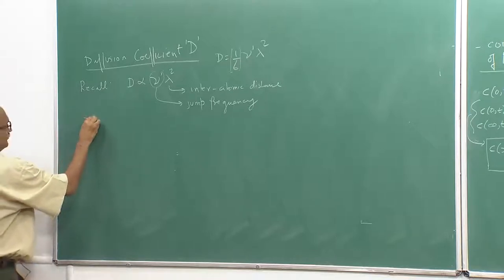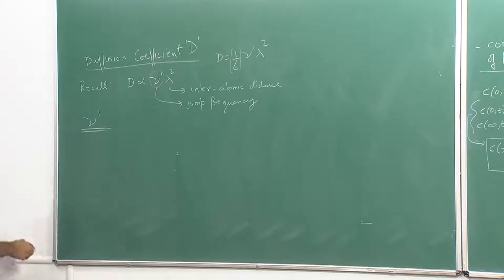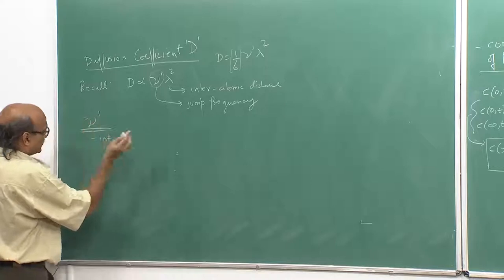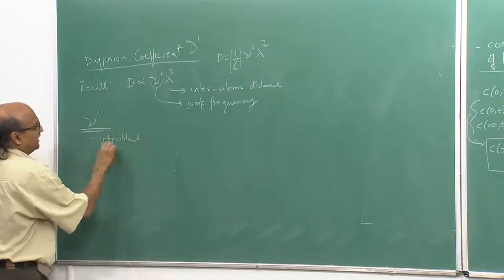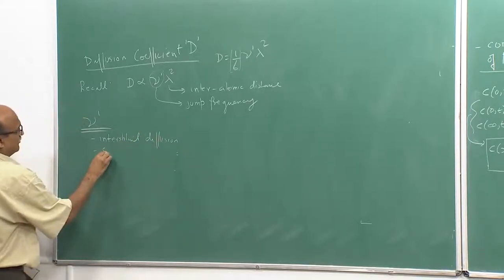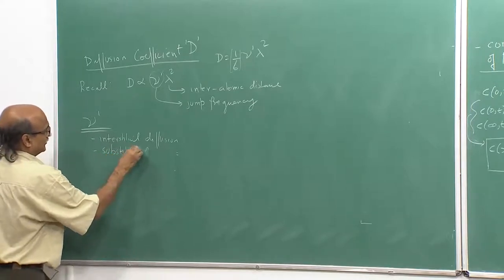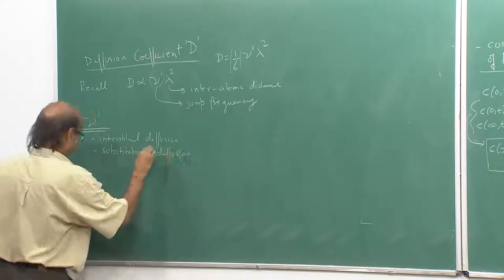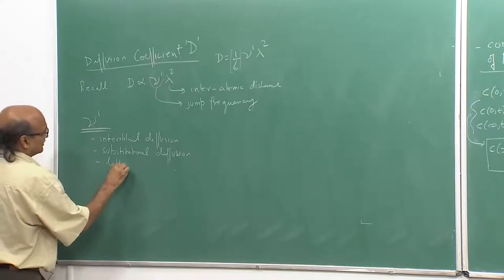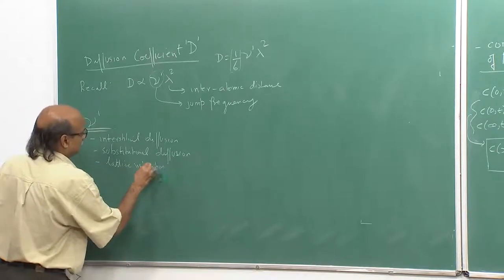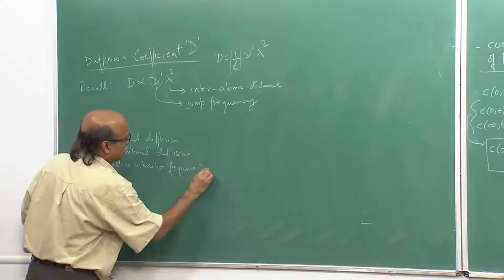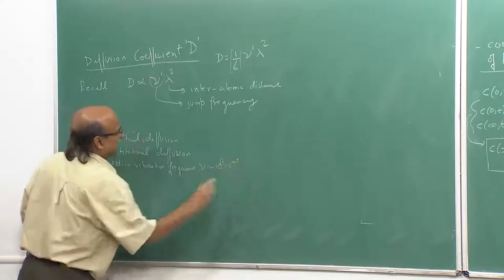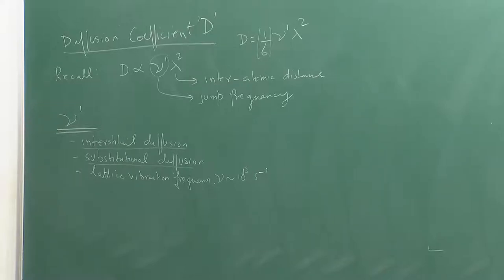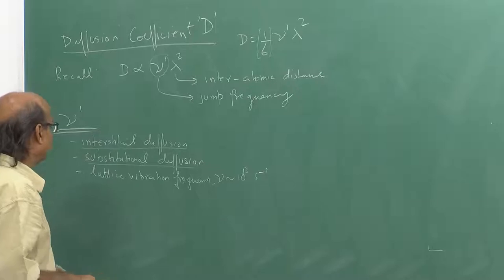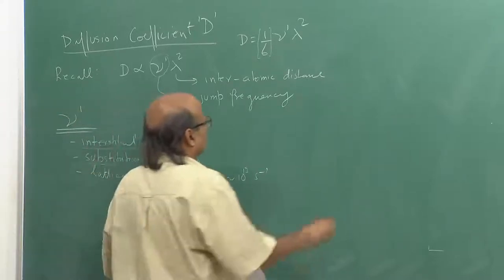What is it going to depend on? Well, first of all, it will depend on the mechanism of this diffusion, whether we have interstitial diffusion or substitutional diffusion. And it would also be dependent on the lattice vibration frequency, nu, which can generally be taken as 10 to the power 13 per second. So let us examine the two cases of interstitial and substitutional diffusion and how the jump frequency is going to depend on these two mechanisms. So let us consider interstitial diffusion.